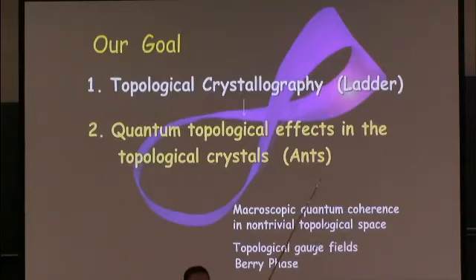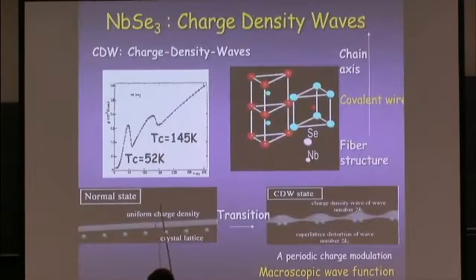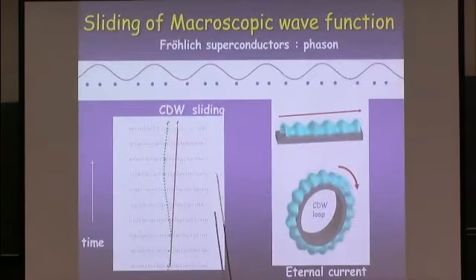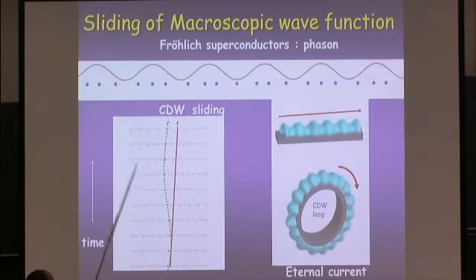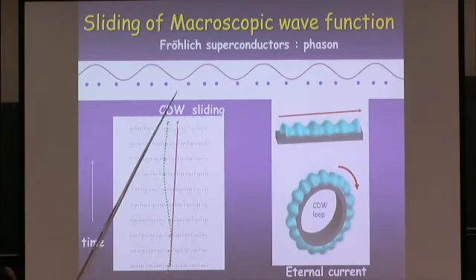next we show the quantum topological effect in the topological crystals. NbSe3 undergoes charge density wave transitions, electrons forming a macroscopic wave function, at 145 Kelvin and 52 Kelvin. And the charge density wave can slide without friction. Atoms only oscillate, but the macroscopic wave function is sliding. It is called a Fröhlich superconductor.